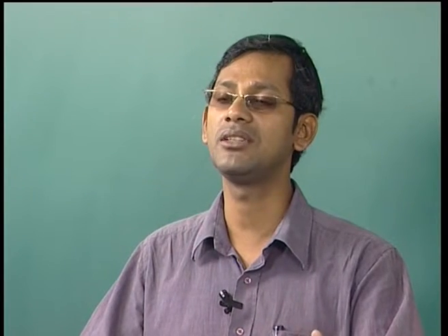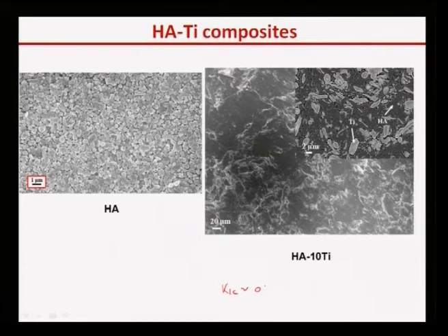Therefore most biomedical applications require development of new materials. One such material which is important for both dental and bone applications is hydroxyapatite based, and hydroxyapatite is a novel material in the sense that it is biocompatible and bioactive. That means once it goes in the body, it allows the cells to grow on it and helps the cell regeneration process and many other things. But there is a problem. Hydroxyapatite is very brittle. Its fracture toughness K1C is basically 0.5 MPa root meter, which is very low. Normal bone has a fracture toughness between 2 to 12.